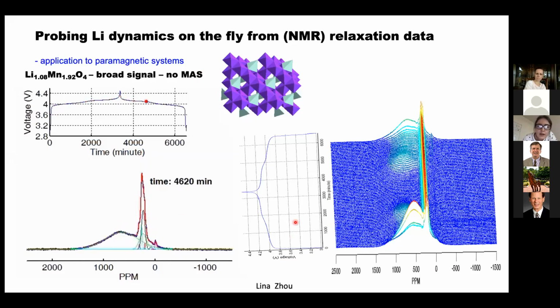But if you now look, instead of at the movie, just look at the stack plot, you can see here's the signal, it goes away, and that's not too surprising because you pulled all the lithium out of it. But what was surprising to us is that at 0.5, you actually see an increase in the intensity. And if you think about that for a while, NMR is meant to be quantitative.